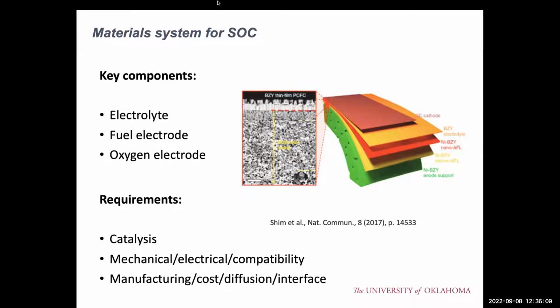Secondly, for each component, the electrolyte is just a single component of either fluorite or perovskite material. And the fuel electrode is a mixture of nickel oxide and the electrolyte materials. This is a very thick layer, which supports the entire SOC. And the nickel oxide can be reduced to nickel during the operating process by the hydrogen, and then nickel is a catalyst for the fuel electrode side.